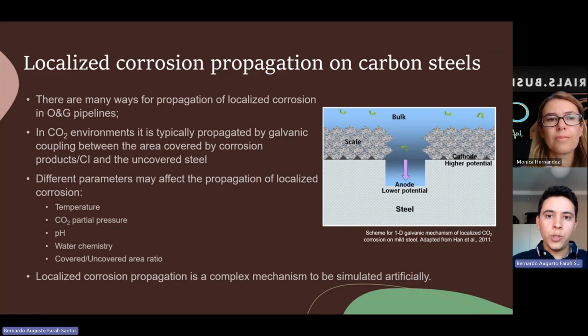So usually what happens is that the area in which the pit is being corroded tends to have a lower potential locally. Of course, if we consider the pipeline as a whole, it should have the same potential. But locally, when we are talking about local phenomena, it has a lower potential compared to the surrounding areas which are covered with corrosion products or corrosion inhibitor. And this difference in potential, as we know from the theory, and we have an electrolyte for the electrons to flow. So a galvanic coupling is established between these areas.